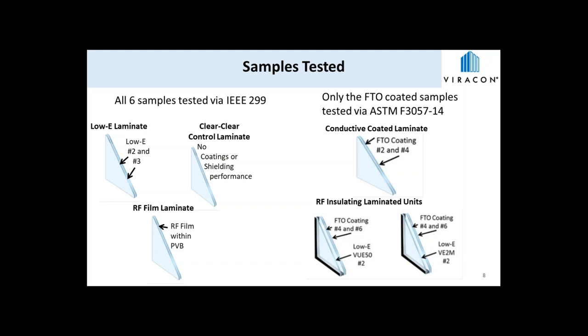The RF film laminate, which has an RF film within the PVB inner layer, and we went ahead and included a clear control laminate, tested as a control, which has no coating or shielding performance additions. Of the samples that were tested under both of the methods, so this would be the three samples on the right-hand side, this includes a conductive coated laminate with two layers of a fluorine doped tin oxide coating, or